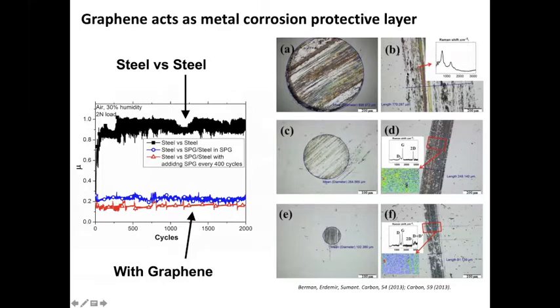At the top row, you see the wear of unprotected steel. In the case of just bare steel sliding against each other, they generate lots of corrosion, lots of oxidation on the surfaces, which you can see from the color changes, from the large wear track size, and from the Raman shift, the Raman signature.